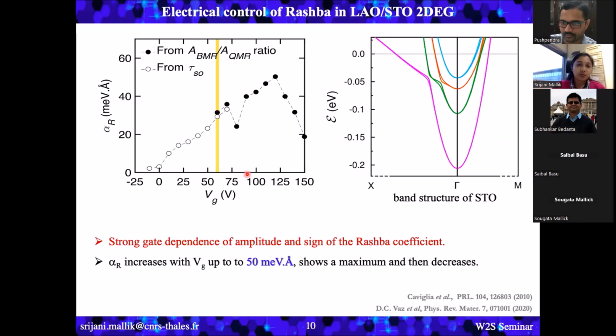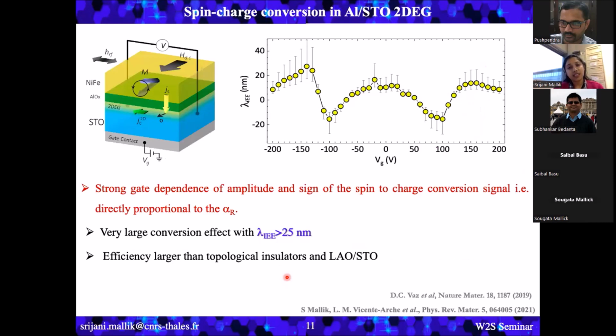So to do so, we, along with other groups, tried the electrical control of Rashba in lanthanum aluminate and strontium titanate two-dimensional electron gas. And what people found is there is a strong gate dependence of the amplitude and sign of the Rashba coefficient. So far, the highest alpha value for a specific gate voltage was found to be 50 millielectron volt angstrom. Then the spin to charge conversion was studied in aluminium STO 2DEGs, because I just showed you that alpha varies a lot with the gate voltage. So a strong gate dependence was also found for the spin to charge conversion. And extremely large conversion efficiency was found for aluminium STO, close to 25 nanometer, which is much larger than topological insulators or the LAO/STO 2DEGs, let's say.